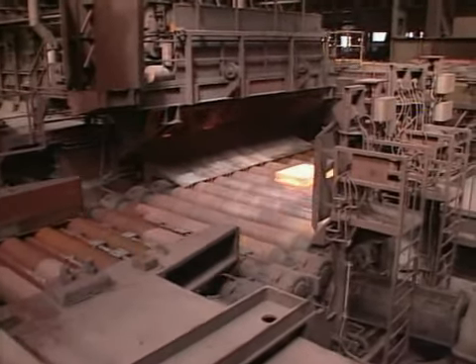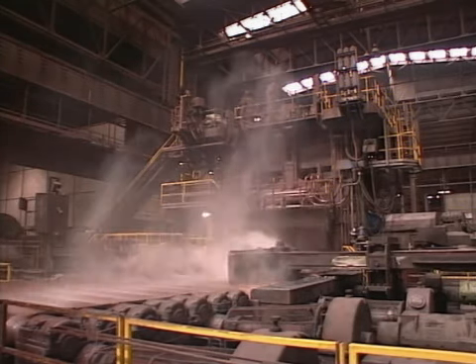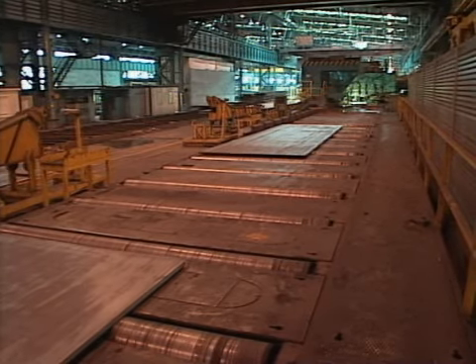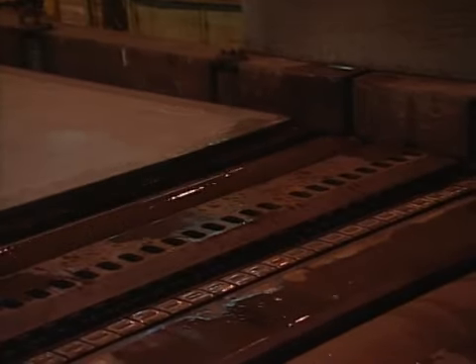After positioning, the slab is rolled between 2 rolls, making the slab thinner, wider and longer. The rolling is performed in several steps by reversing the slab through the rolls and turning the plates 90 degrees to roll it in 2 directions. This is done to create material properties that will be as uniform as possible in both directions of the plate. The final step in the plate rolling operation is thermomechanical rolling, where the plate is rolled at a relatively low temperature, followed by intense water cooling.